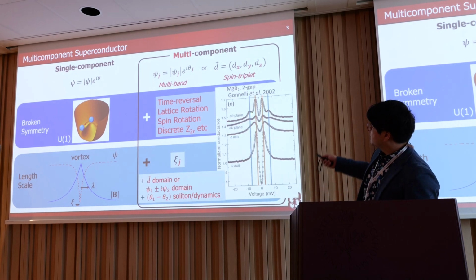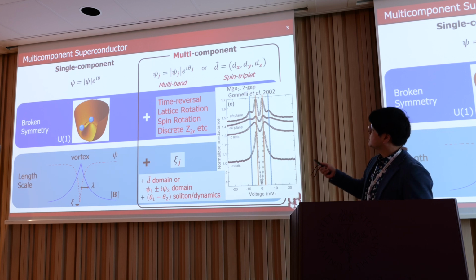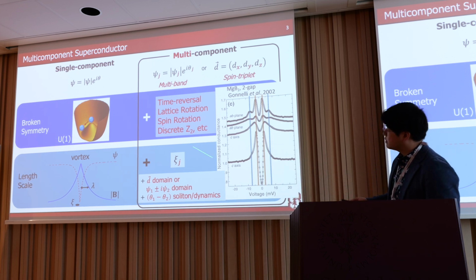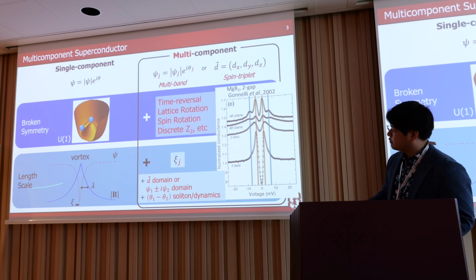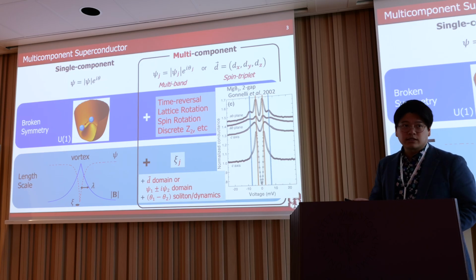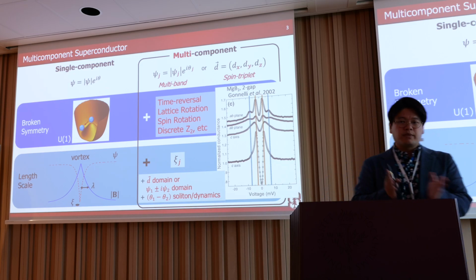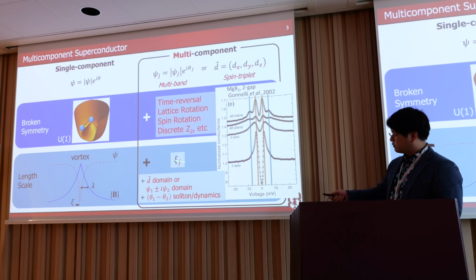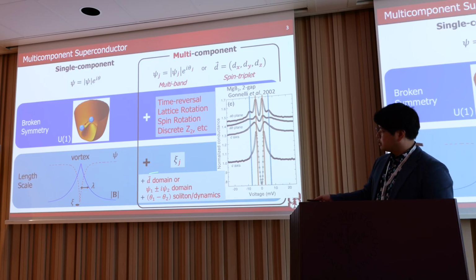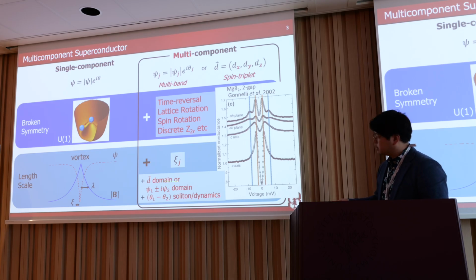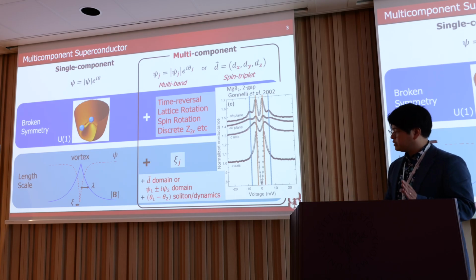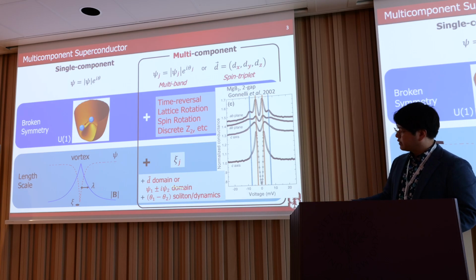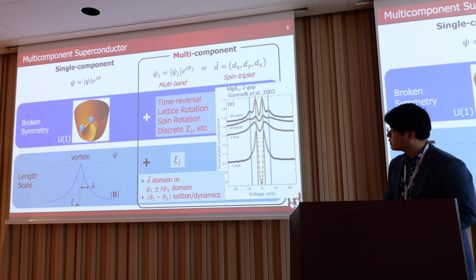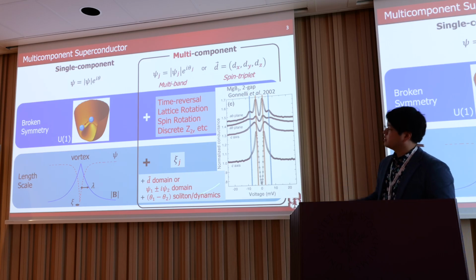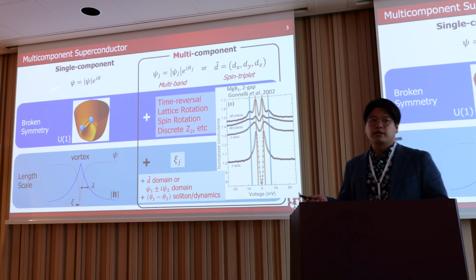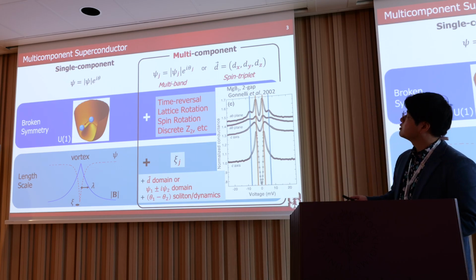And the famous multiband, two-band superconductor MgB2 has two gaps and has an additional length scale. The coherence length is characterized for each band. And for some short range, like d-vector domains or chiral domains, each band face different dynamics. So a very complicated nature is introduced by the multicomponent superconductor.